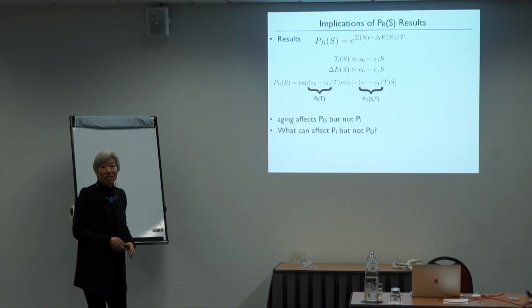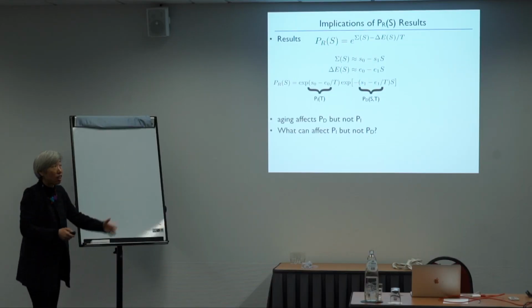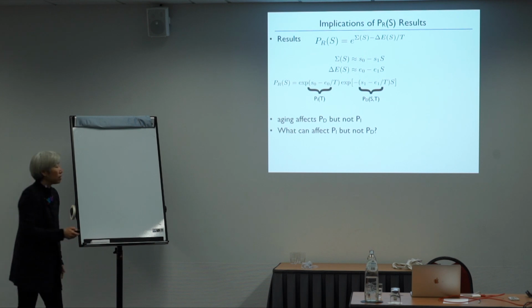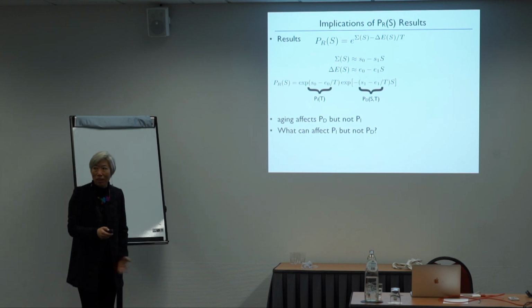So we thought, let's look at thin films of glasses. Because if I'm in a thin film, then how big that energy barrier is depends on how close I am to the surface of the film. It should get smaller as I go to the surface of the film. And that would be a way to change this piece. Let's see if this piece changes. Maybe the softness changes too, though. So we thought thin films are an interesting problem.